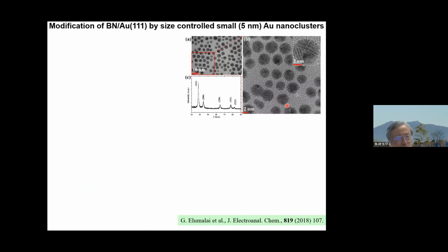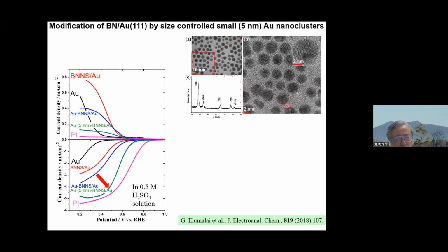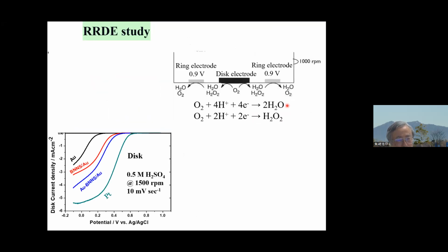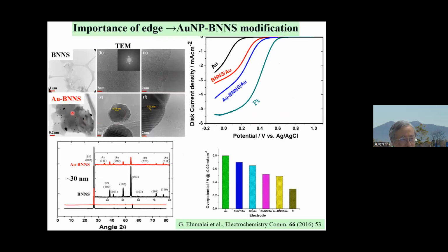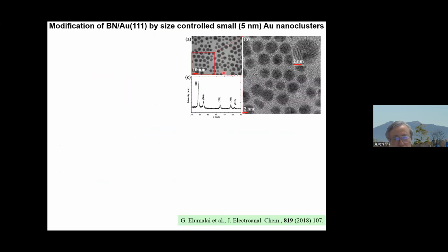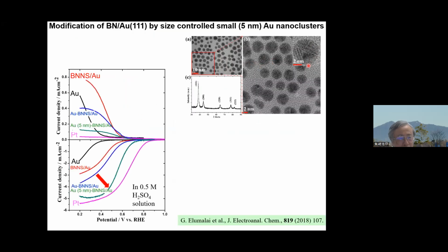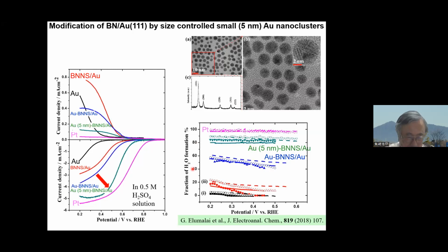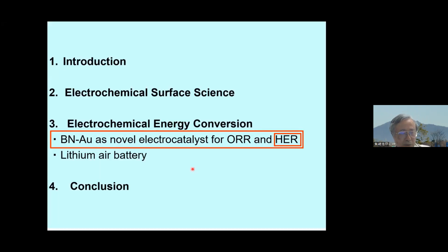That's what we thought. Then we used size-controlled small gold nanoclusters, in this case 5 nanometer clusters. Before, the gold nanoclusters were randomly distributed, but in this case we controlled the size of the gold nanocluster to 5 nanometers. So this is the result. Compared with even this one, it's very close to platinum. The disk current increases, the ring current decreases. So the fraction of water formation is almost 80%, very close to platinum.